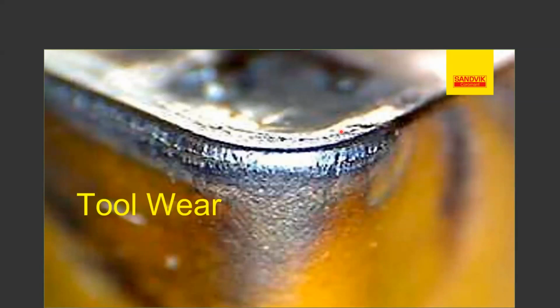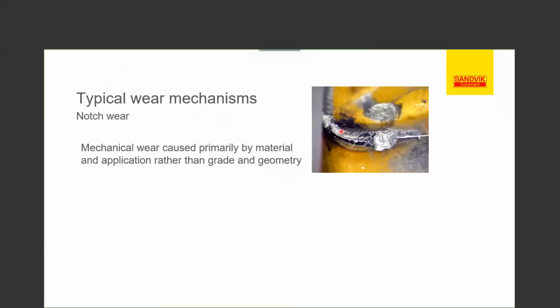Next, we want to look at the tool wear. What type of typical tool wear do we get when we're machining these types of material? Frankly, the most common is going to be our notch wear. Is typical on the depth of cut we're running our insert. So what happens is you get a little heat propagation area right here. And what happens is you get that buildup of heat right there, and that's what creates the notch. Eventually, that notch will turn into a whole edge line breakage.